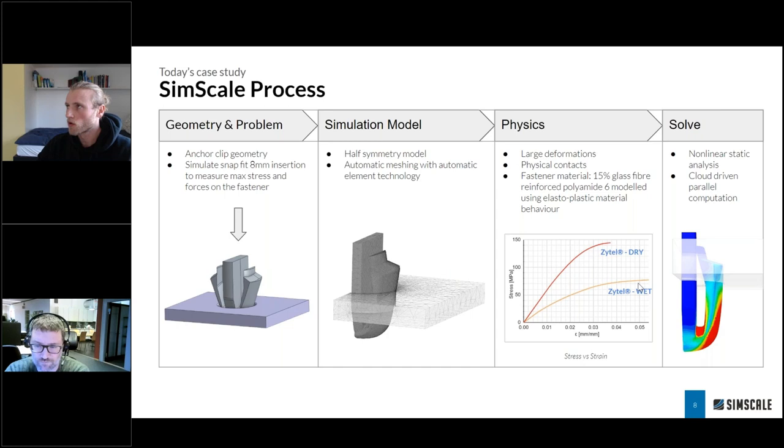But Massimo, what are the materials in reality? Would they be the fully wet or the fully dry? It's hard. The problem with polyamide is that it varies very much with the moisture that is in the atmosphere. So that's why in Sweden we tend to use POM most of the time, to avoid this kind of flexure. I know that in Southern Europe, in France and in Italy, they are more into the polyamide. Depending on 23 degrees, 50% moisture, we are in between there.